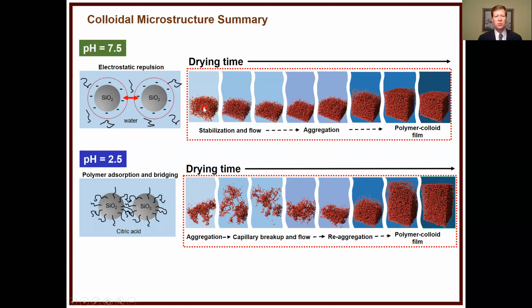With that, I just want to give you a quick summary. At pH 7.5, we believe the particles are not attractive. They have a very weak interaction. What we see is stabilization of that film and flow, and then eventually we may see aggregation through depletion, but there's no evidence of that in the plots I just showed you, and eventually it makes this very dense polymer colloid film. And then in contrast, we can have a heteroaggregated system where the particles are attracted to each other through these essentially heteroaggregated polymer branches. Now you can see that you essentially start with a very open gel that changes its microstructure drastically and then leaves you with a structure that may or may not have similar properties.